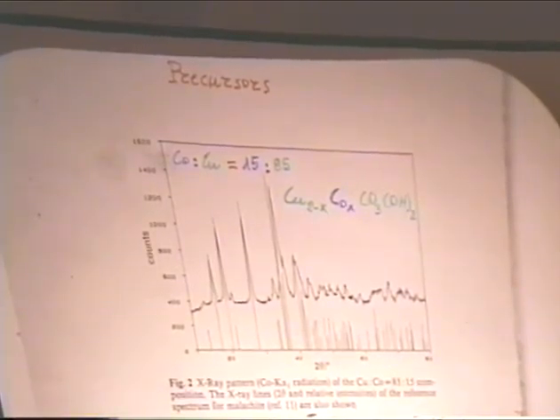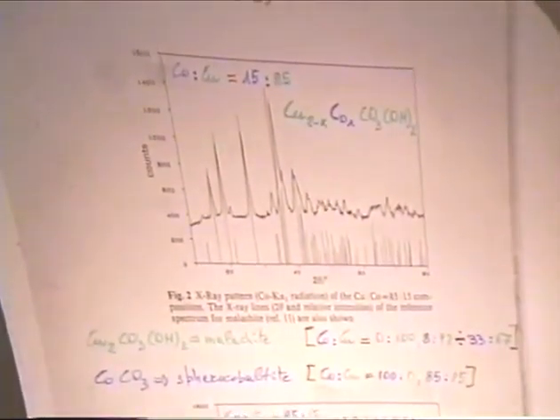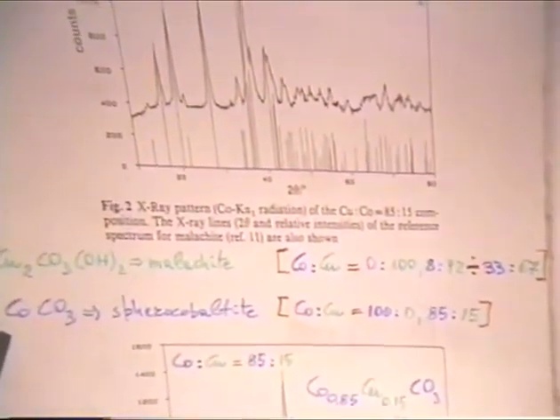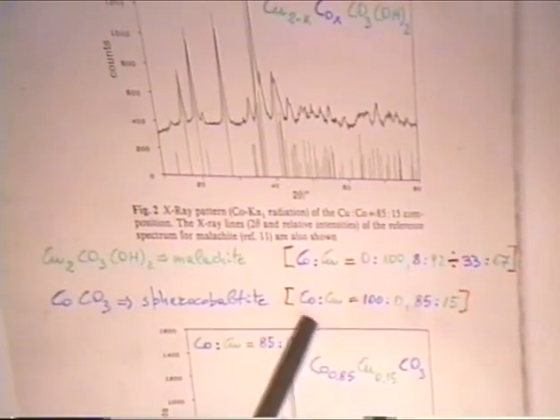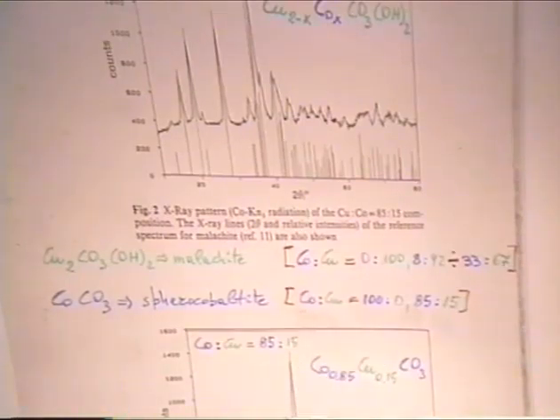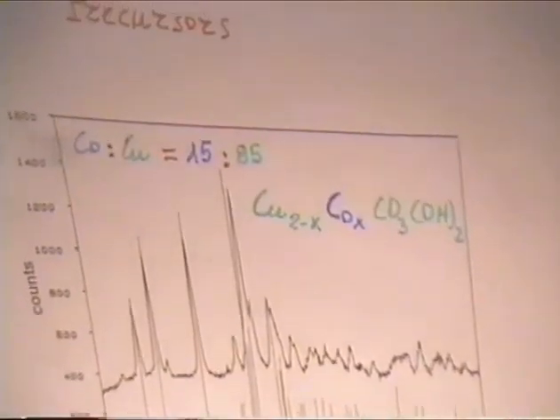However, today I will give you some details about the surface properties of the cobalt copper mixed oxide catalysts and of their reduction behavior in nitrogen. But first, I want to show briefly the X-ray diffraction analysis results for the precursors. Well, for the specimen containing only cobalt, namely for the cobalt copper 100:0 atomic ratio composition, the pure cobalt carbonate, spherocobaltite,